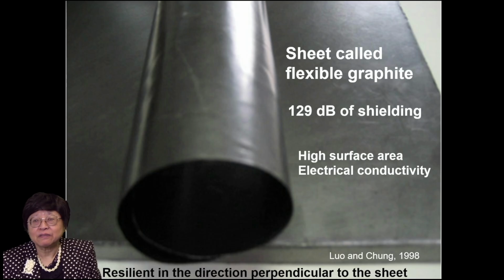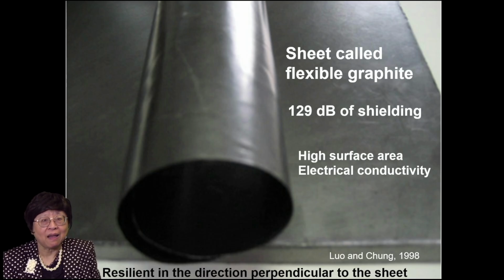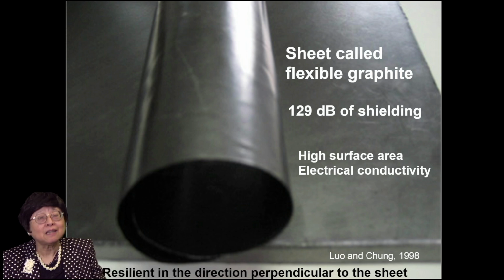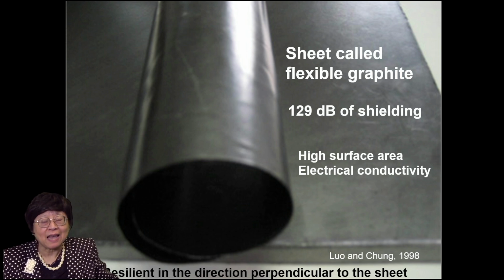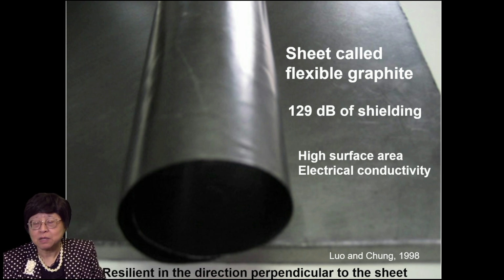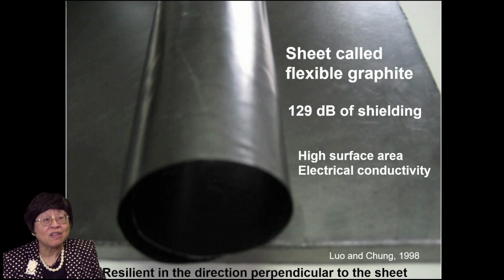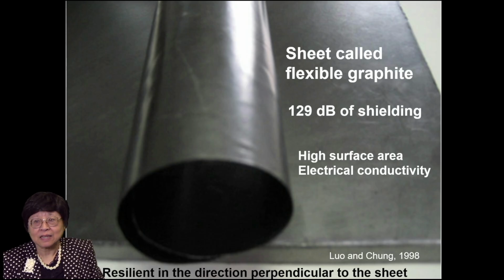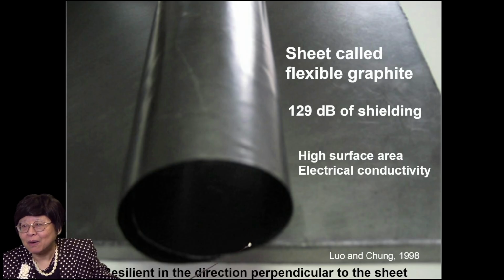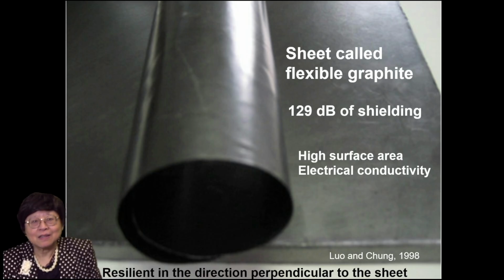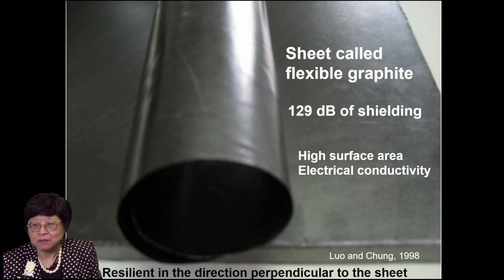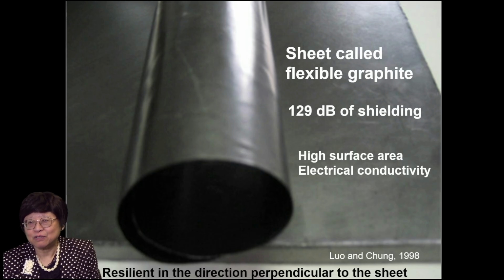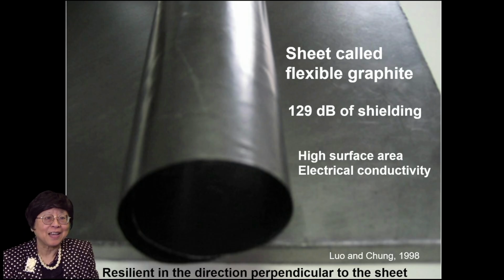And if we have a pile of these worms and compact this pile, because of the cellular structure of each worm, there is mechanical interlocking among these worms. So it forms a sheet without any binder. It's all graphite. And this sheet is flexible, so it's called flexible graphite. And we discovered a long time ago that this material is superb for shielding. 129 dB of shielding. That is the highest you can measure.